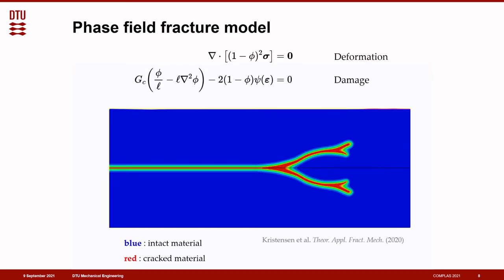And just by solving this simple system of equations, we can capture on the original finite element mesh in both 2D and 3D very complex cracking patterns like the one I'm showing on the screen. This is a crack branching due to the application of a dynamic load. So we can capture both branching and merging of cracks, nucleation from arbitrary sites, and complex crack trajectories without any convergence issues and no need for remeshing.